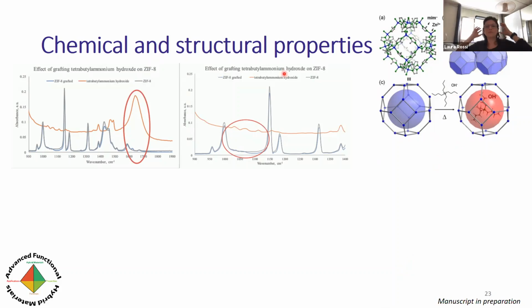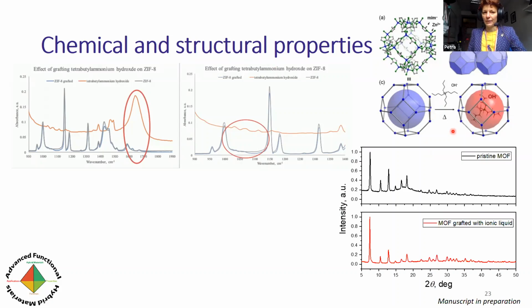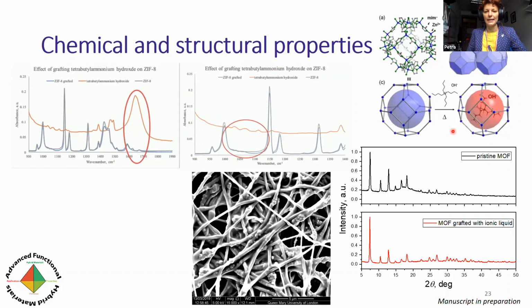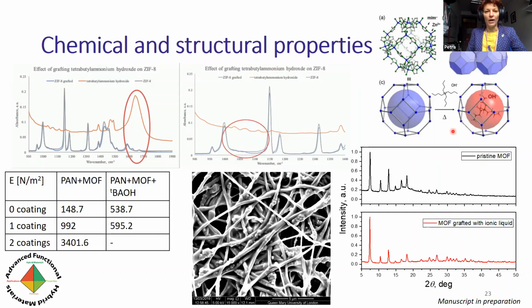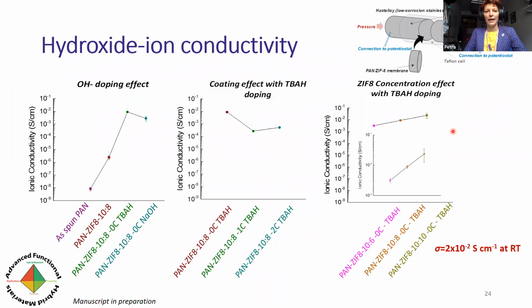Sorry about that. So of course we looked at whether or not we can graft the ionic liquid on it, and we also demonstrated that the framework crystallinity is retained while also retaining some good mechanical properties. And I suppose the most important thing is the hydroxide ion conductivity itself. So we got actually over 100 times improvement with respect to the powder material.